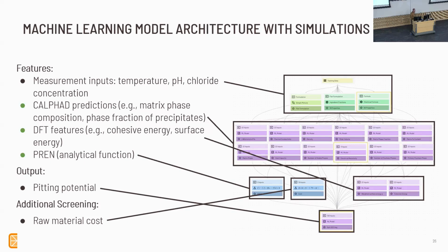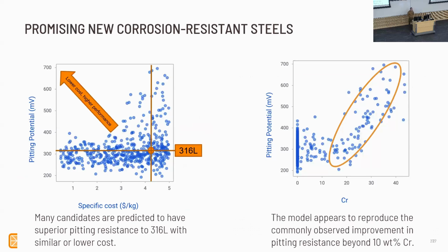And then we also have a simple model for raw material cost, which is basically just the cost of the elements. So putting all this together, we were able to look at possible new corrosion-resistant steels, where the plot on the left corresponds to predictions of specific cost, so the cost per unit kilogram, and the pitting potential. And these are all novel alloys, steels specifically, that we generated with just a simple generative model from Monte Carlo. And you can see 316L there at the pinpoint. What you're looking for are things on the upper left for low cost, high performance. And you can see that there's actually quite a bit of possibility here for something that outperforms 316L.